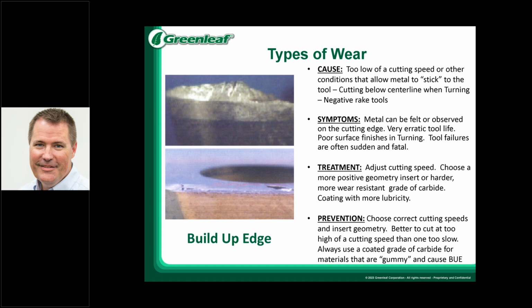Looking at ways to either find a more positive chip form, a grade that can hold its edge strong is important as well. If you are seeing this type of wear, it's just a matter of time before you'll end up getting into a chipping operation as well, because as that material builds up, new material can weld onto it, actually then pull off the coating and small carbides along the edge of your insert, which is going to shorten the tool life for your insert as well.